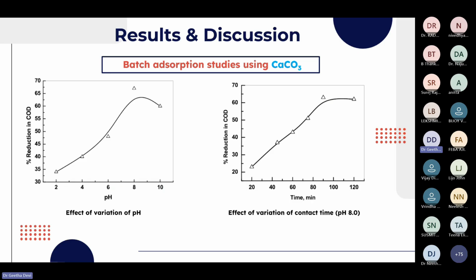First we started with calcium carbonate, and we could see that as pH increases, the percentage reduction in COD increases, and maximum reduction occurred at a pH of 8. Here the contact time was varied, keeping this optimum pH for the next experiments, from 20 to 120 minutes, and we could see that 90 minutes gives higher COD removal.